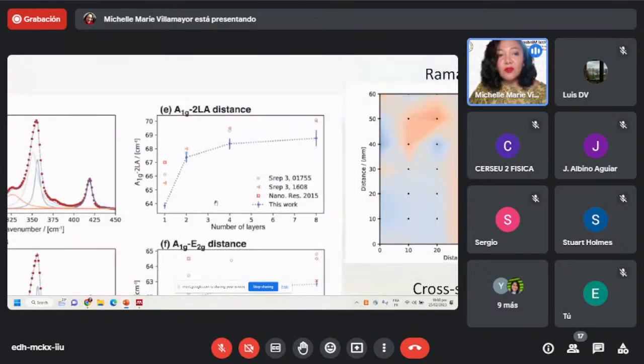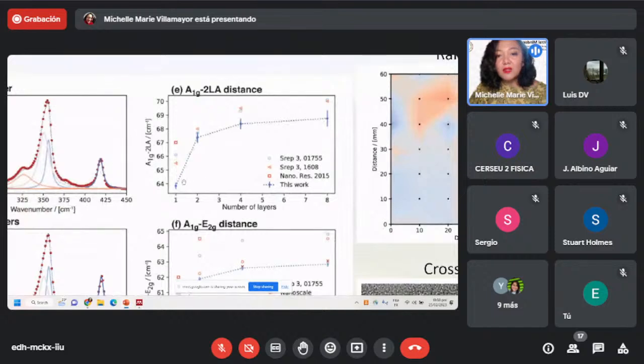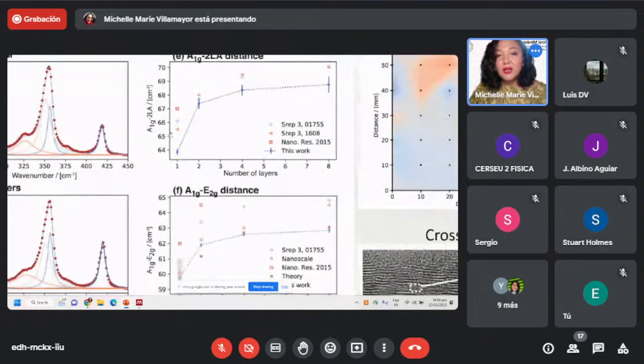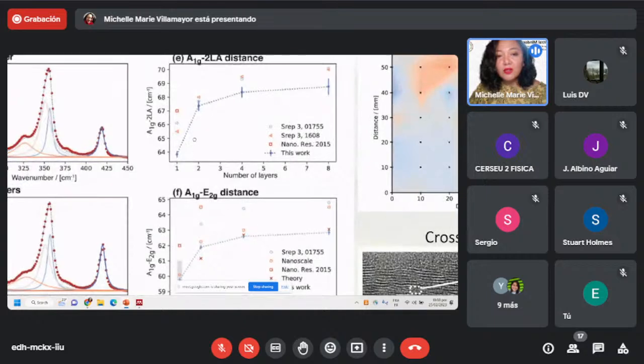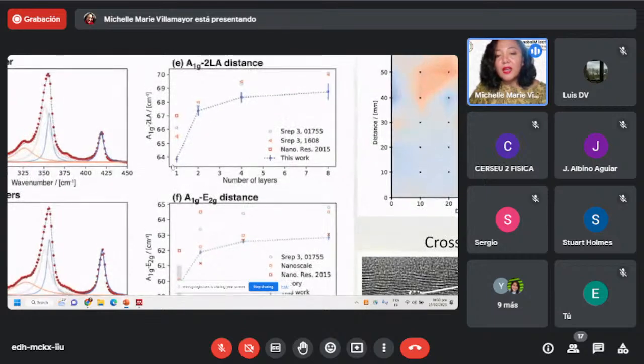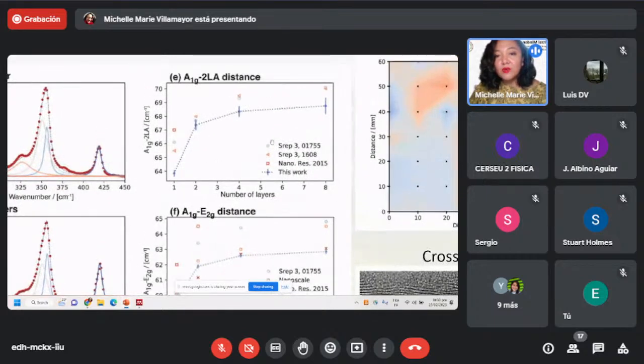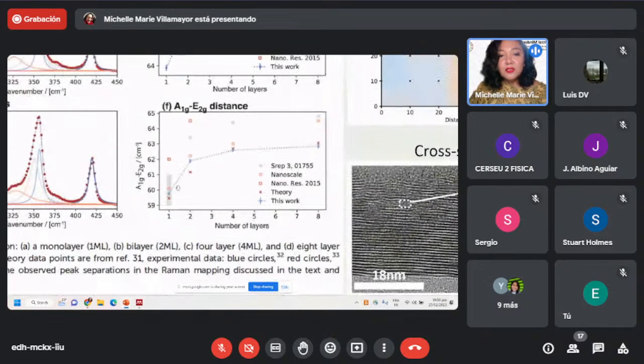So we checked for a particular peak, and if the peak separation is small, then we know that it's a monolayer, and we have compared our results to other publications. For the monolayer in the 4-inch wafer, we have found that our results are the same or almost the same as the published results, which are in theory and also done in experiments.